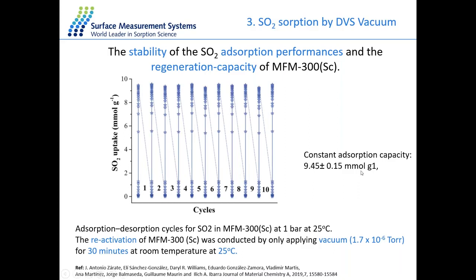And you can see the sorption capacity for the 10 different cycles is almost the same, around 9.45 plus minus 0.15. That means this MOF material is very stable in this kind of toxic gas environment, and it can remain the sorption capacity or the performance for very long-term use.